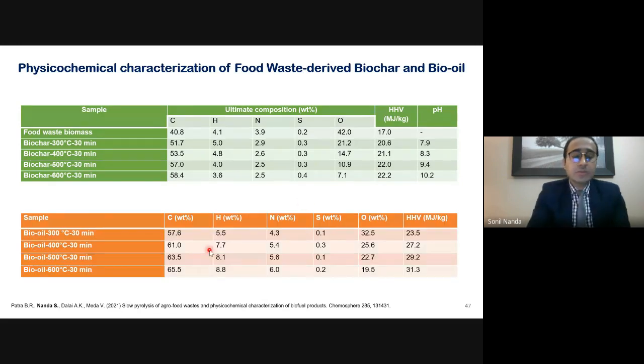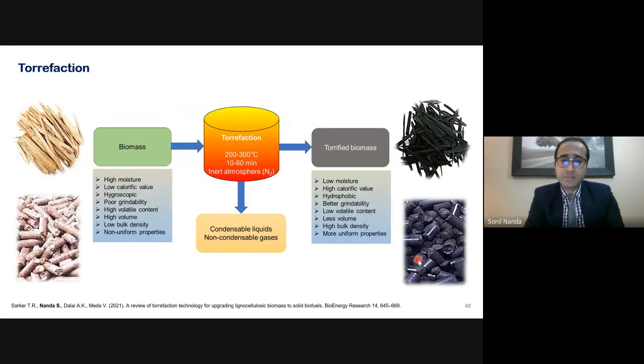Now, coming to the bio-oil, the CHNS analysis of the bio-oils also shows the same trend as that of the biochar. So the bio-oil also tends to have high carbon content and high hydrogen content and lower oxygen content when produced at higher temperatures. Once again, as the carbon content increased and the oxygen content decreased, the heating value of the bio-oil was also increasing gradually with the increase in the temperature.